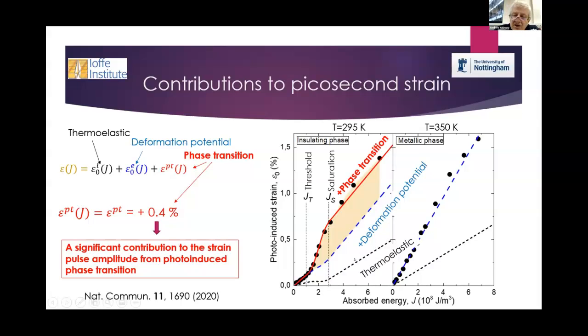So this dashed curve gives us this thermoelastic mechanism, which gives the strain much less, almost one order of magnitude less than what we measure. Then we need to add deformation potential.